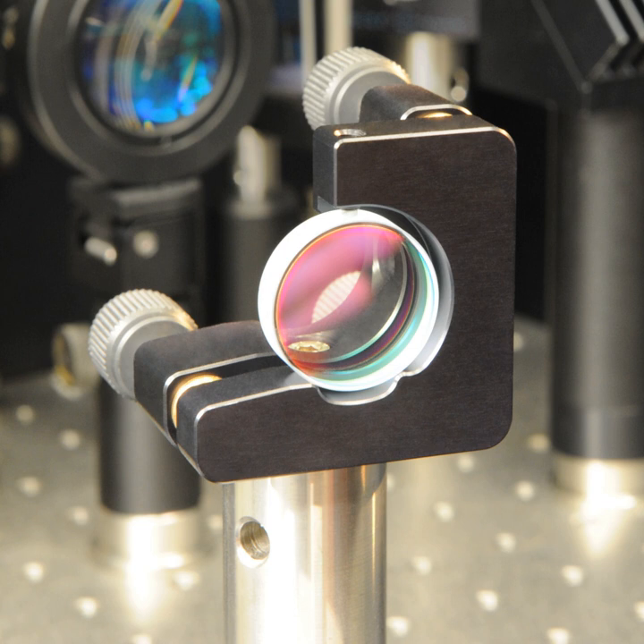Simple dielectric mirrors function like one-dimensional photonic crystals, consisting of a stack of layers with a high refractive index interleaved with layers of a low refractive index.